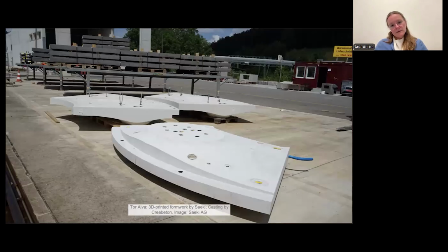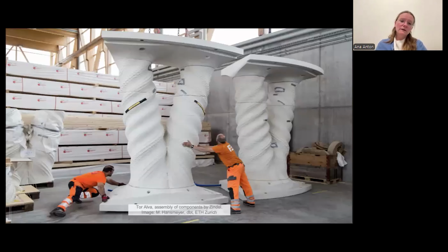The prefabricated bases were delivered to the prefabrication hall together with the 3D printed components, and they were assembled one level at a time. And after one level was assembled, they would be taken on site and assembled on site. It took roughly 2 days to assemble a full column, and the process was parallelized for multiple columns. First, they would stack the elements, introduce the rebars, glue the segments together, wait for 24 hours for the glue to set, and then the thin grout could be added in the hollow channels to fill and bond the vertical reinforcement.